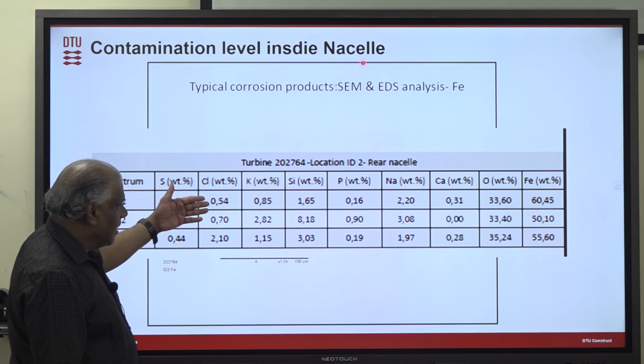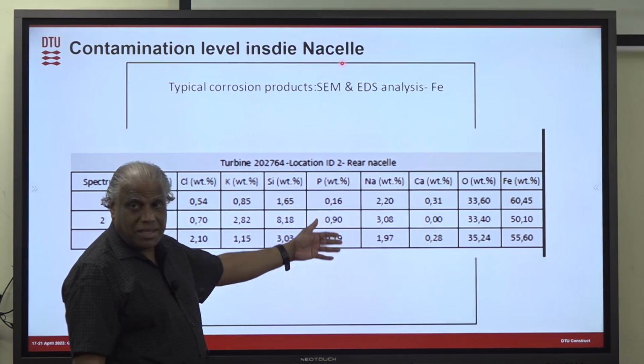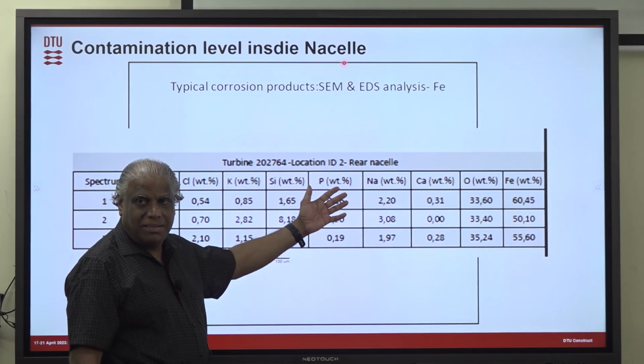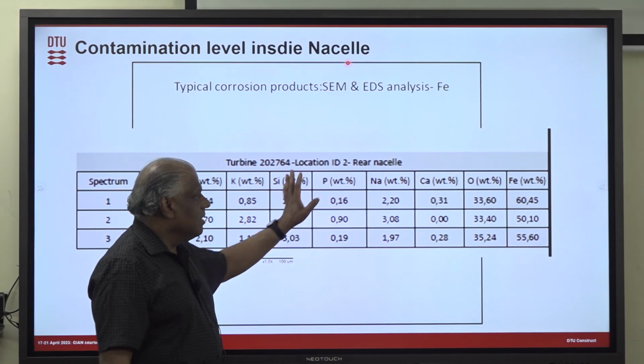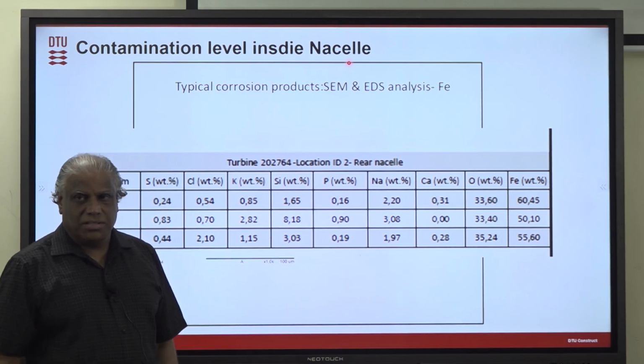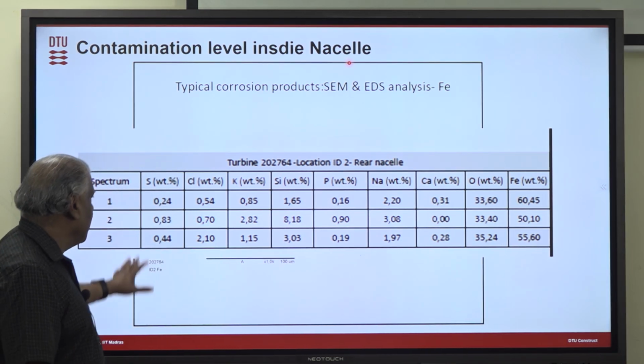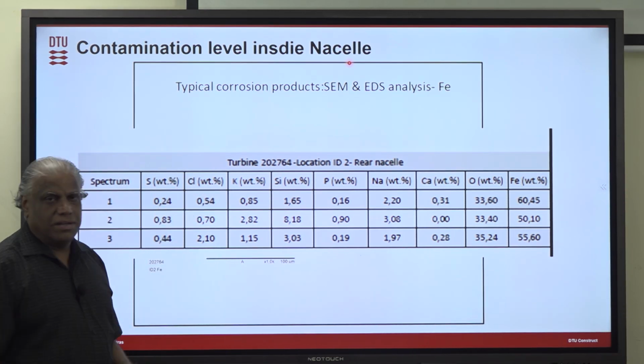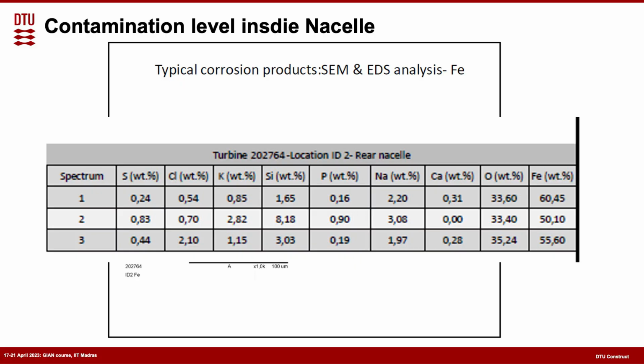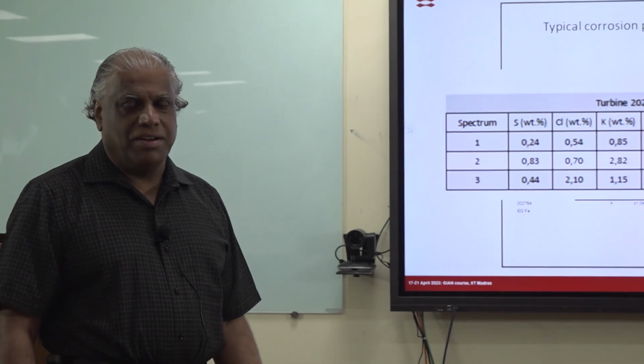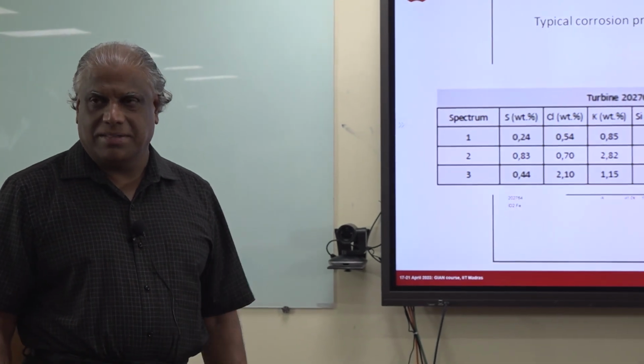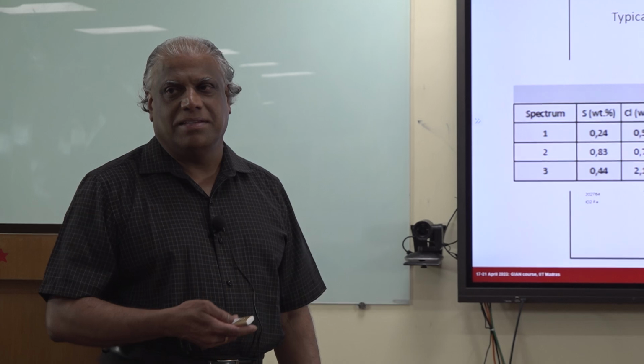We couldn't explain everything at the same time, that is why this phosphorus is coming and so on, because it's too complex actually. But ignoring the things which we don't expect, if you take the other one, at least we can see that there is chloride and sulfur. And we have also seen that when we go to a farmland and measure the sulfur gases, we could see that there are sulfur gases in the air.